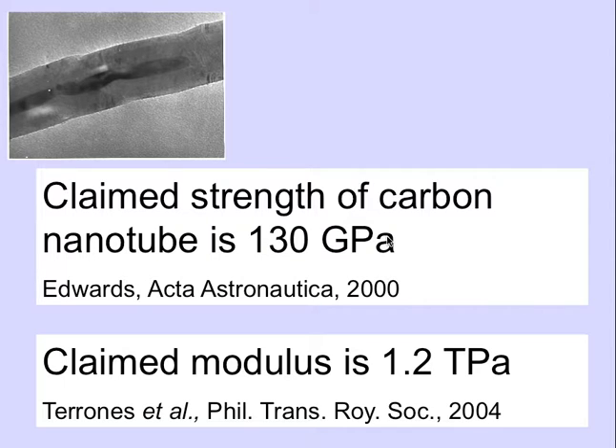Then we come to carbon nanotubes, which had a lot of publicity in the past 20 years. The strength is 130 gigapascals, modulus along its length is 1.2 terapascals - six times that of steel. Headlines in newspapers said engineers are salivating at carbon nanotubes which will replace steel. This is in a journal called Acta Astronautica because lots of money was spent on space elevators.